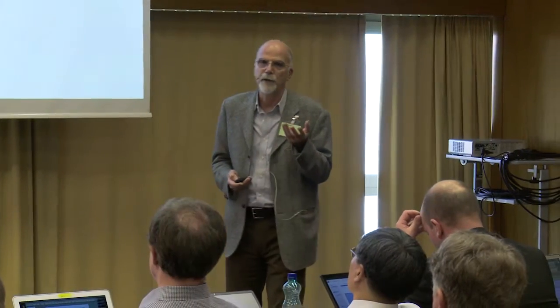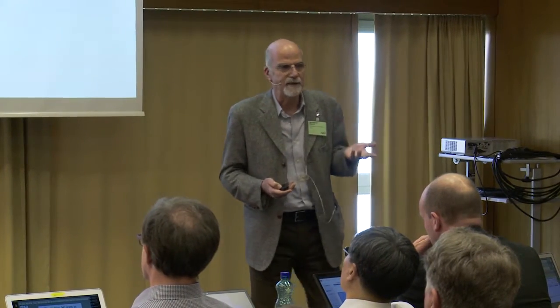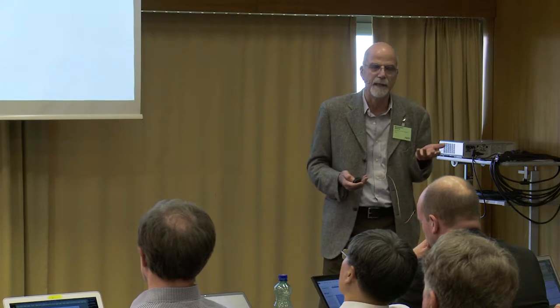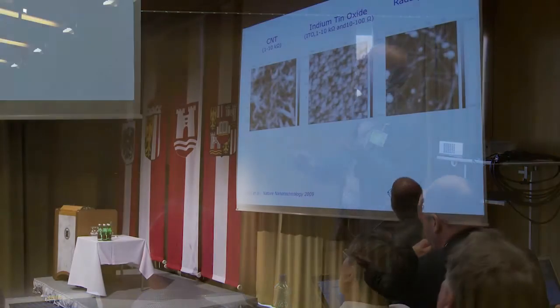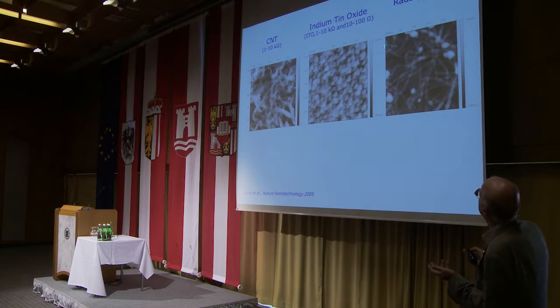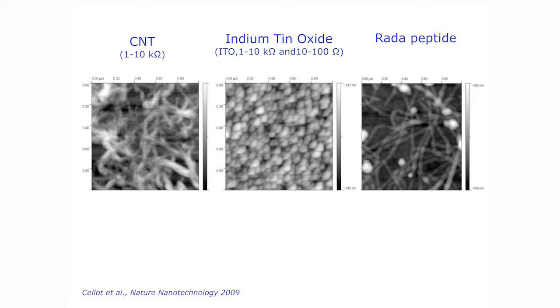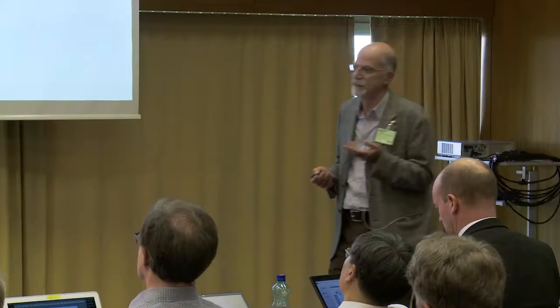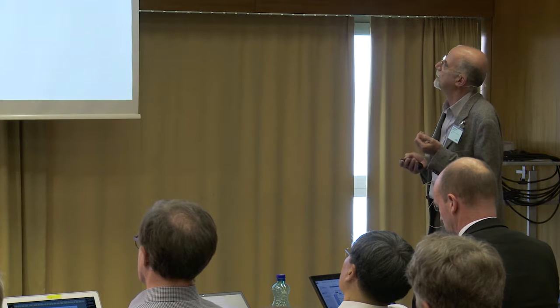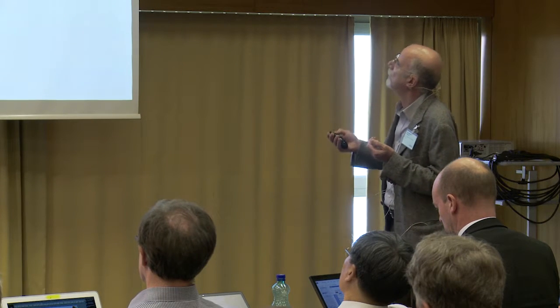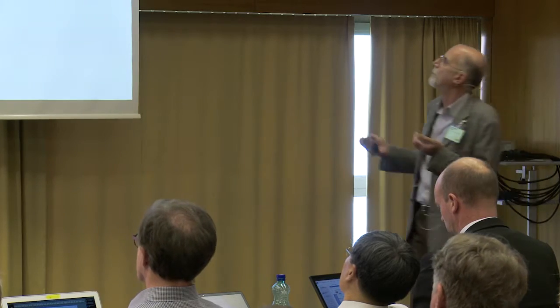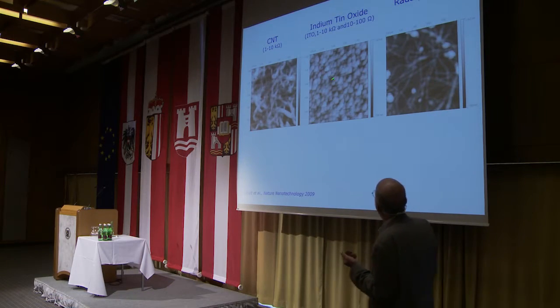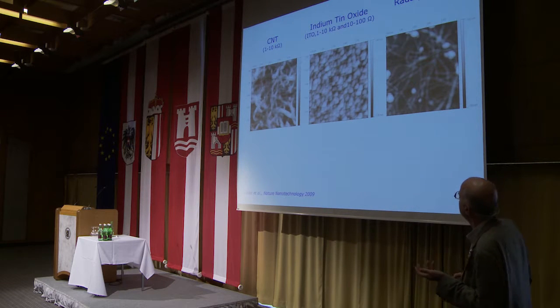So at this point, we thought there might be other materials, other than carbon nanotubes, that can play this role of increasing the interactions between neurons. And so we decided to use different materials. For instance, indium tin oxide has the same resistivity as carbon nanotubes. Or we used a self-assembling peptide, which assembles into a nanotube shape. So this is reminiscent of the shape of carbon nanotubes, but is not conducting. The other is conducting, but does not have the cylindrical shape of carbon nanotubes.